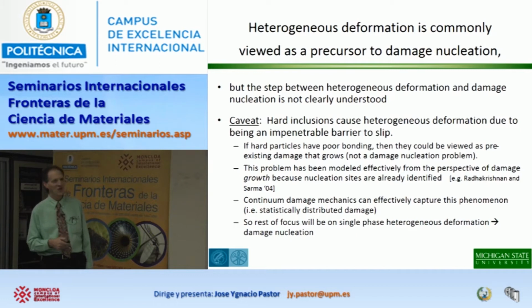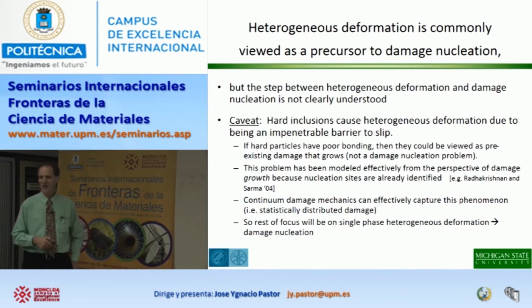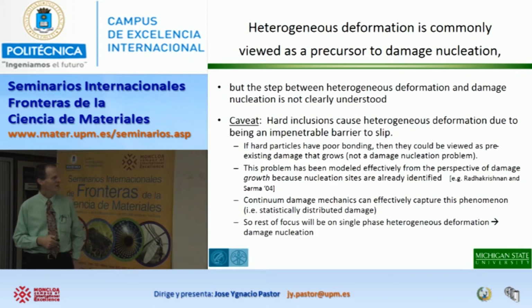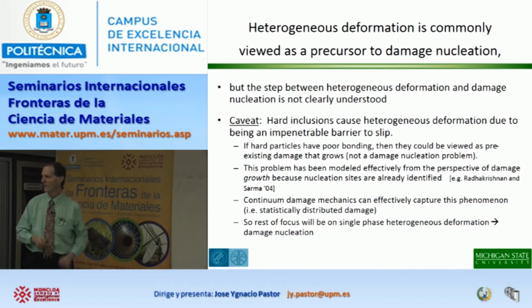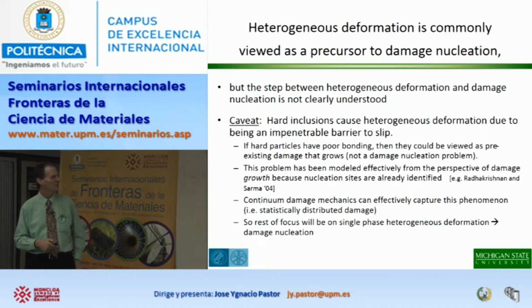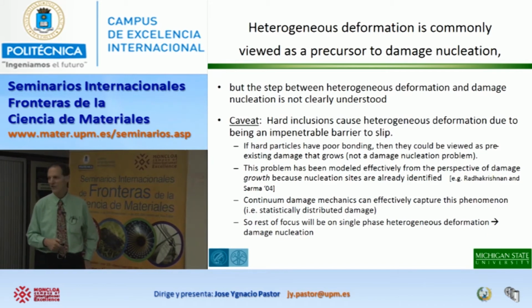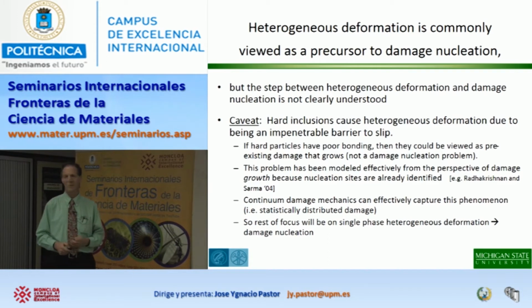Although heterogeneous deformation is commonly viewed as a precursor to damage nucleation, the step between heterogeneous deformation and damage nucleation is not so clear. But I want to make a side step for just a moment, a caveat. One of the places where damage nucleation is pretty easy to find is at hard inclusions. Like in aluminum alloys, there are typical constituent particles that are typically iron aluminide. And they often, in the process of rolling or deformation, will crack. And thus, we can have hard particles that may not have perfect bonding, and they may crack. And thus, we have lots of cracks that are already initially present in an aluminum alloy.